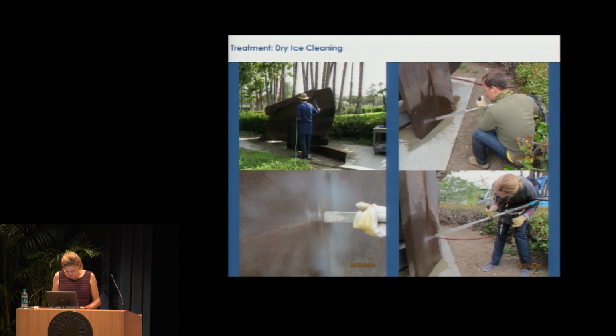As I mentioned, we used 2 containers of dry ice, so about 1,000 pounds a day. And they were delivered fresh every day. So in total, we used 12 containers of dry ice. For the whole project, we ended up using 6,029 pounds of dry ice. It sounds like a lot, but you go through it quite fast. And the total rental and the dry ice, everything, costed less than $5,600. So we were quite on budget with that.